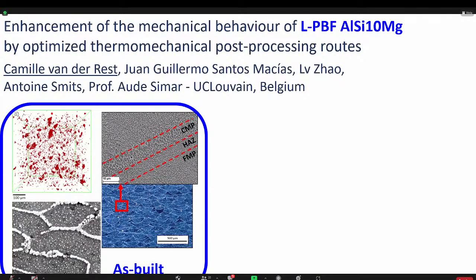So this afternoon, I will talk to you about aluminum, silicon, and magnesium processed by laser powder bed fusion. First of all, about the as-built material, it is well known that it has a significant amount of porosity after the process. It also has a specific mesostructure with some melt pools visible, and a typical microstructure with a silicon network being the white phase here, and also some silicon-rich precipitates, which are the white dots inside the aluminum matrix.